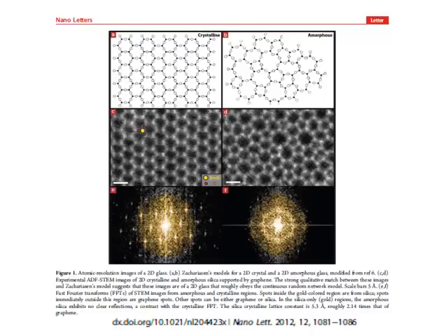The study identifies the glass as silica formed from a bilayer of SiO4 tetrahedra without detectable covalent bonding to graphene. These guys claimed that, by accident, they demonstrated a new class of 2D glass that can be applied in layered graphene devices and studied at the atomic scale.